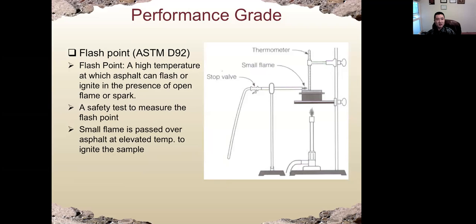This is another test. It's called flash point. Okay, because we do not want asphalt pavement to burn after a car accident. We want to know what the flash point for asphalt is. For this test, it's pretty simple. We just increase the temperature of asphalt, and then after several seconds, we pass a small flame on the top surface of the asphalt, and we see what the flash point for the asphalt cement is. Okay, so this is a safety test to measure the flash point of the asphalt cement.